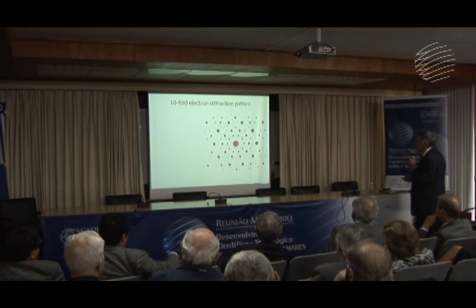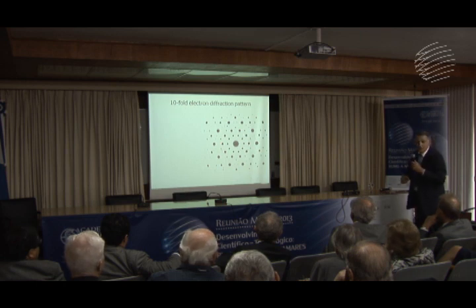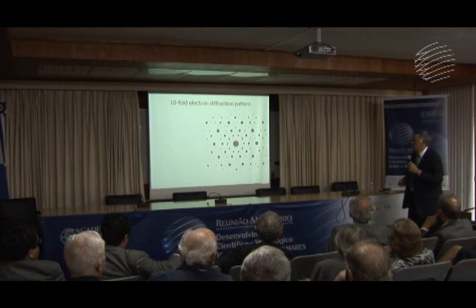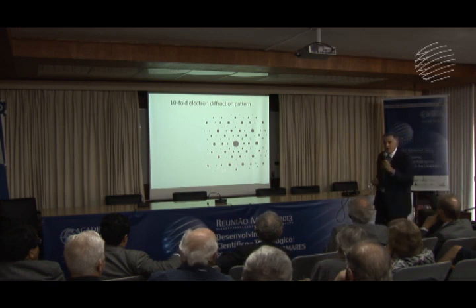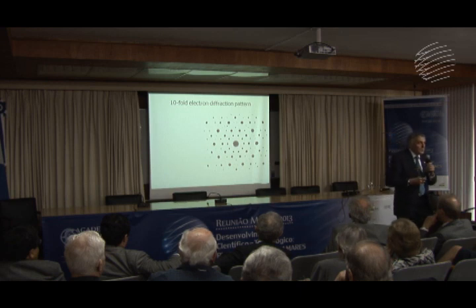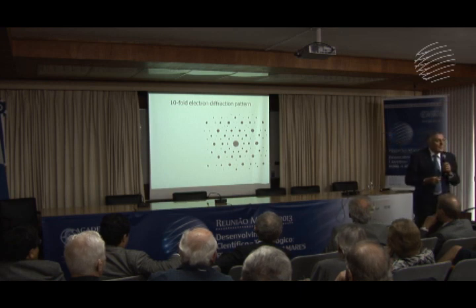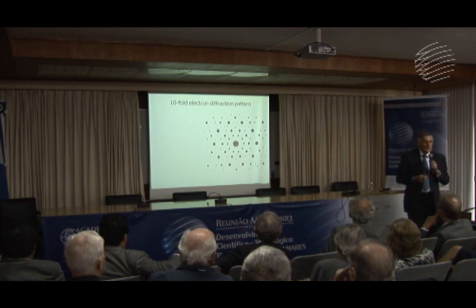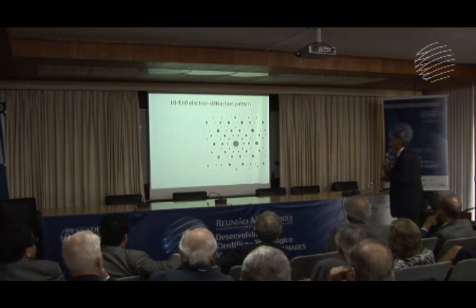This is the transmitted beam, central point. I look at the rotation symmetry, and I start to count. 1, 2, 3, 4, 5, 6, 7, 8, 9, 10. No, cannot be. 1, 2, 3, 4, 5, 6, 7, 8, 9, 10. Tenfold, three question marks? That's very odd. But there is one more thing which is very important here. You remember the previous electron diffraction pattern? It was periodic. Now here, there is no periodicity. Periodicity has gone.